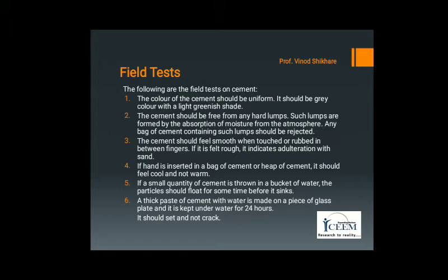Next, the cement should feel smooth when touched or rubbed between fingers. If it feels rough, it indicates adulteration with sand. If a hand is inserted in a bag of cement or heap of cement, it should feel cool and not warm. Warmth means a hydration reaction has happened between the cement and moisture or water in the atmosphere.